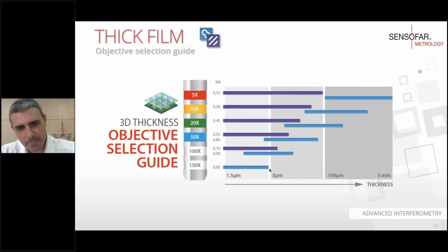But on the other side, we see an upper limit, and the upper limit is again the same as confocal. The reason is that every time we focus through a transparent material, optical aberrations appear because of this focusing, spherical, coma and other aberrations, and the contrast decreases. That contrast loss completely destroys the information inside the material, and that is creating this upper limit. What's the base for that?